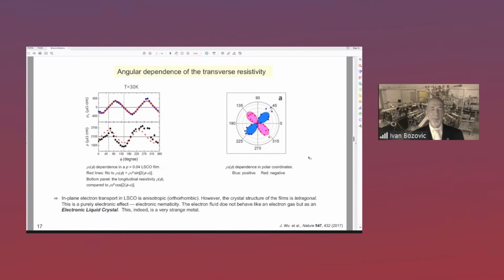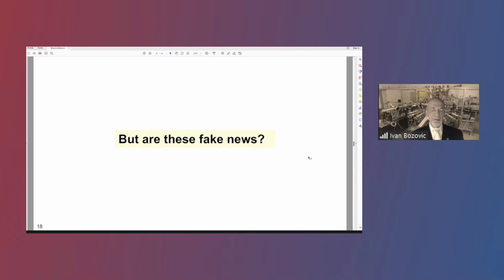We can also plot this in polar coordinates, with the radial distance measuring the amplitude and the azimuthal angle being the angle, and the blue color denotes the positive and the negative values of the transverse voltage. This looks like a cloverleaf pattern, showing that the 4-fold rotational symmetry is broken. However, note that the crystal structure of the film is tetragonal. So one is tempted to claim a great discovery, electronic liquid crystal, a new condensed state of matter. But in America, people say if something is too good to be true, perhaps it isn't. And the bigger the claim, the more one needs to be cautious.